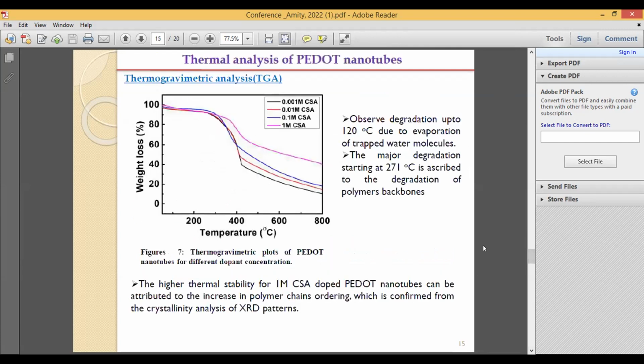Then we have performed thermogravimetric analysis to see the thermal stability of our synthesized samples. Here we have seen that in all the samples, up to about 120 degrees Celsius, degradation was observed, and this may be due to the removal of water trapped inside the polymer chains. Then above 271 degrees Celsius, this may be due to the degradation of the polymer backbones. We have also seen that the high concentration samples show higher stability, and we can correlate this with our XRD results.